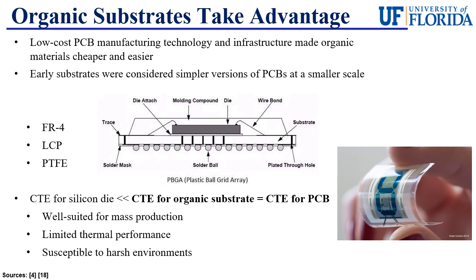Common materials for organic packaging substrates are FR4, a common PCB composite, liquid crystal polymer, or Teflon-based composites. And an important quality of organic substrates is that their coefficient of thermal expansion is well matched to the PCB. This means that the interconnections between the substrate and the PCB will be less affected by thermal fluctuations. And since the coefficient of thermal expansion is much greater than the silicon die, the size of the silicon die will be the factor driving interconnect stress between the die and the substrate.